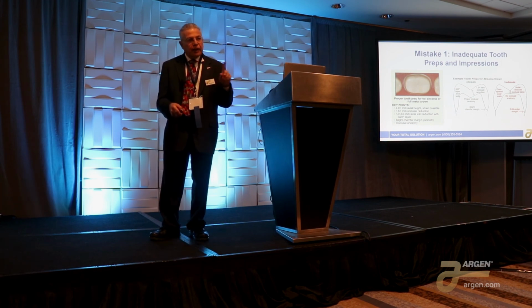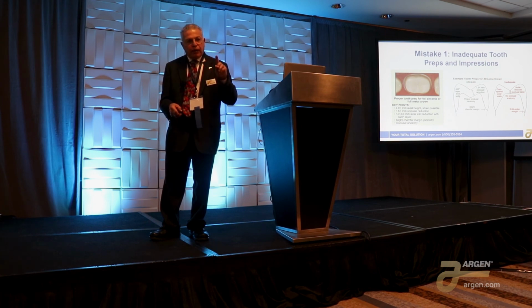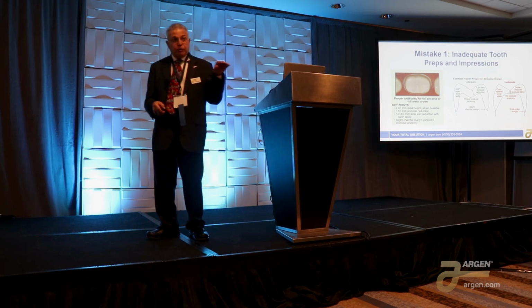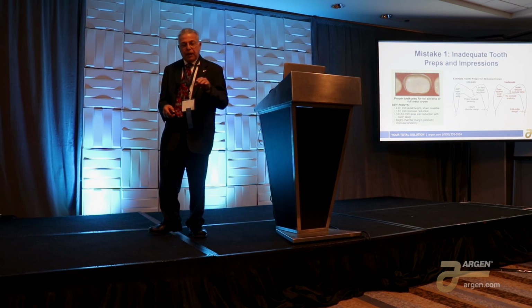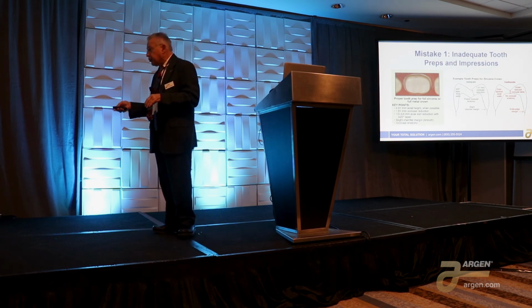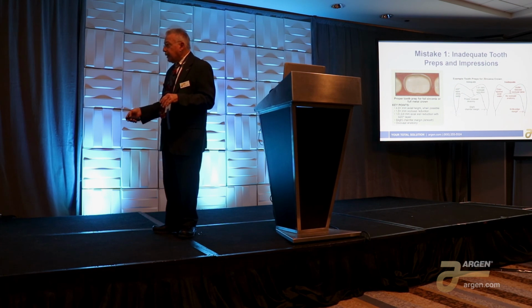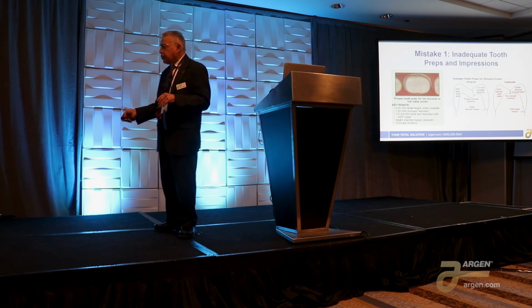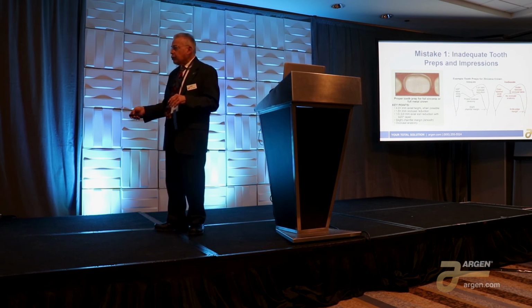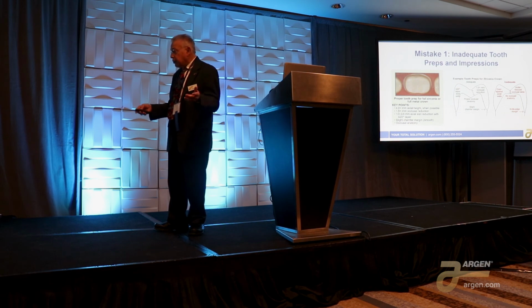In another study by another group, 95% of the fractures all across the board, regardless of how they were made, whether it was zirconia or PFM, were due to the knife edge margins. So no matter what you're looking at, for monolithic zirconia, we want a slight chamfer edge. Okay? And again, the occlusal reduction is very important and dependent on the type of zirconia that you're using.